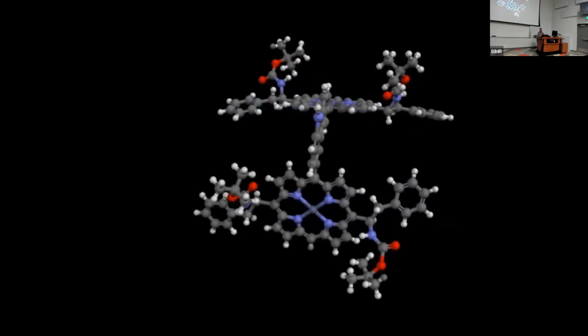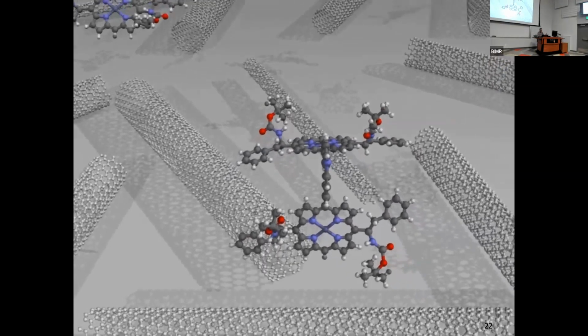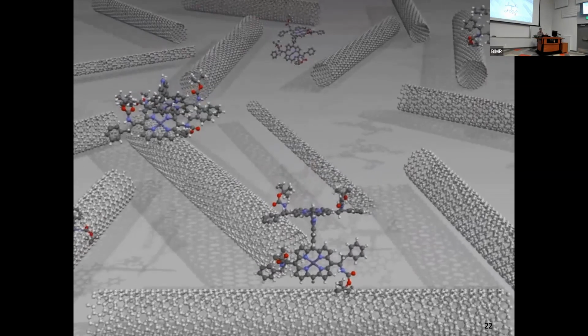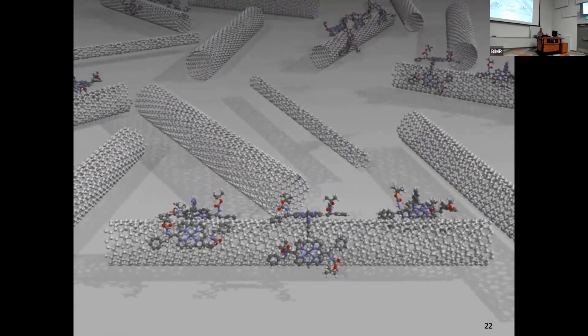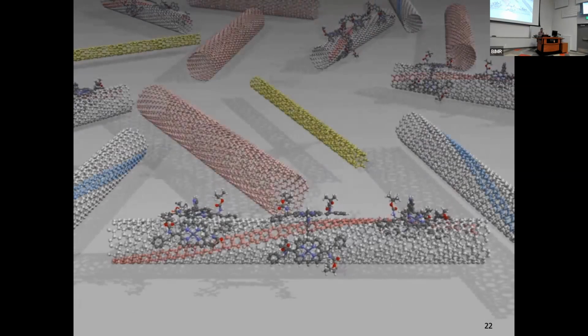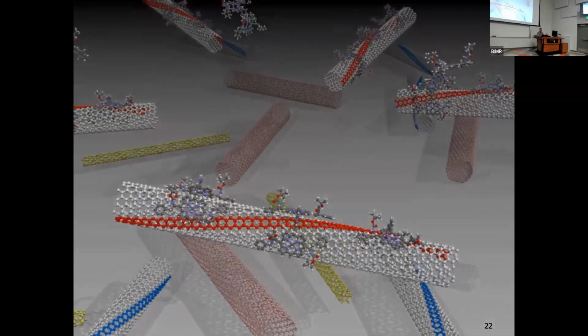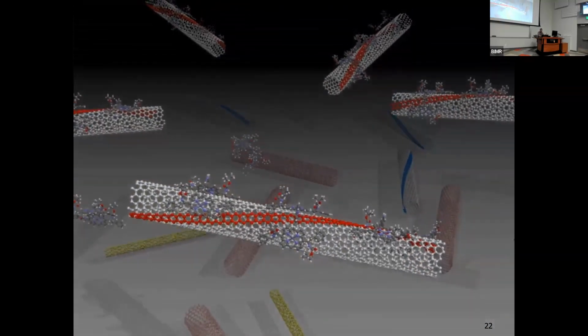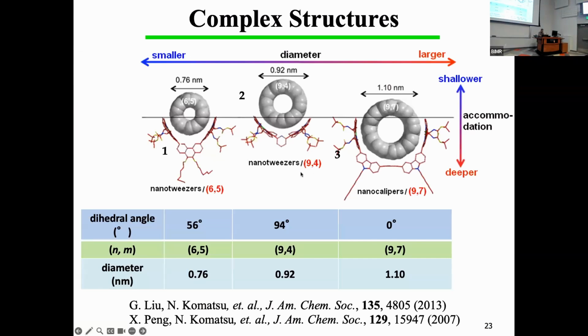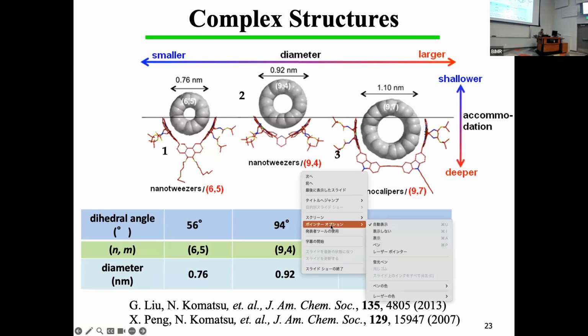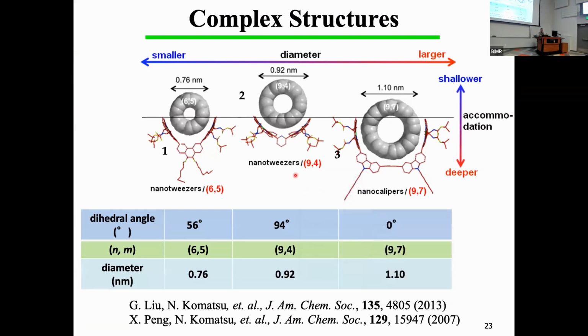So anyway, this is a host molecule with two porphyrin units and a stereogenic center at the periphery. It comes close to the carbon nanotube with appropriate diameter, and it can also recognize left-handed and right-handed structure, and then the nanotube is dispersed in the solution phase. Okay, this is the computer-generated structure of the complex. So you can clearly see how deeply the carbon nanotube was captured in the cavity of the host molecule, in the case of this nanocaliper rather than the nanotweezers.